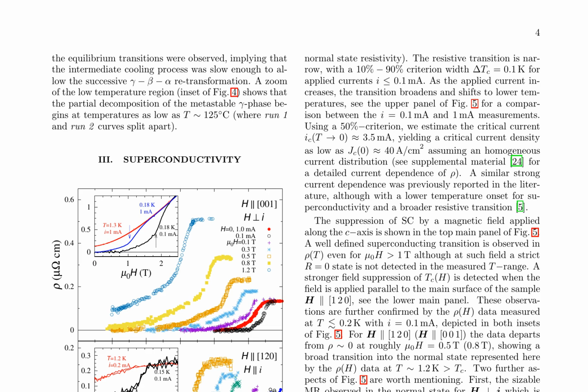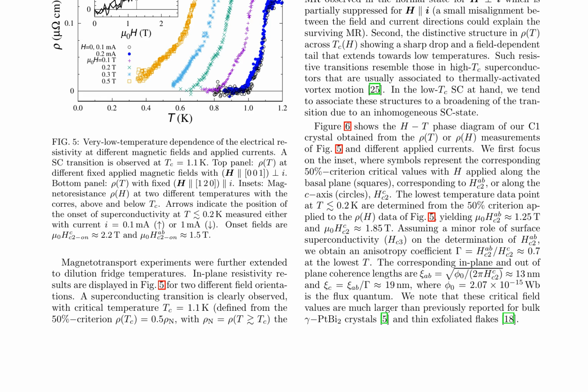The transition is narrow, with a 10%-90% criterion width ΔTc equals 0.1 K for applied currents I less than or equal to 0.1 mA. As the applied current increases, the transition broadens and shifts to lower temperatures. The magnetic field suppression of superconductivity is also observed, showing a well-defined superconducting transition even for strong magnetic fields.